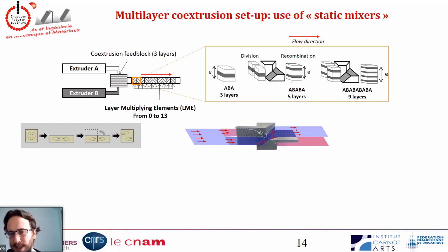So each layer has a thickness that is divided by 2. So here you have 3 layers, you cut and you recombine, you have 5 layers, the total thickness is the same. So basically, each layer has a thickness that is divided by 2. And if you do that one more time, you have 9 layers, and one more time, and one more time. So it's called the baker's transform, and it's how, for example, in Chinese restaurants, you see sometimes they make noodles, or it's how the baker makes the pâte feuilletée in France also.